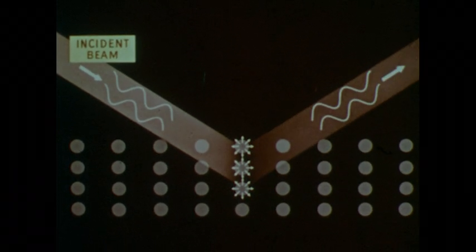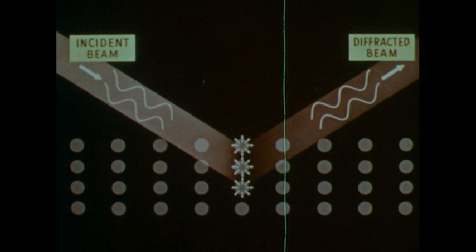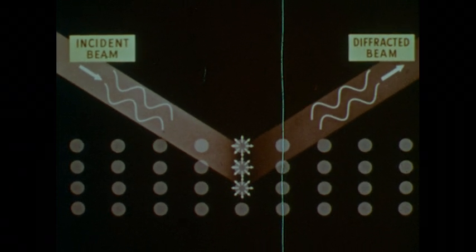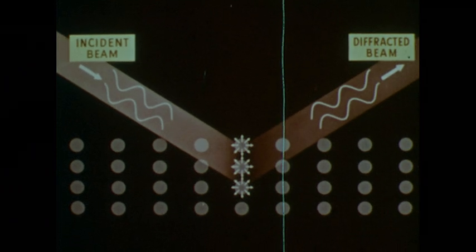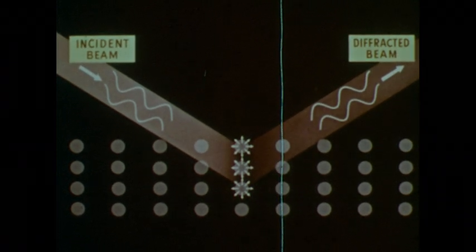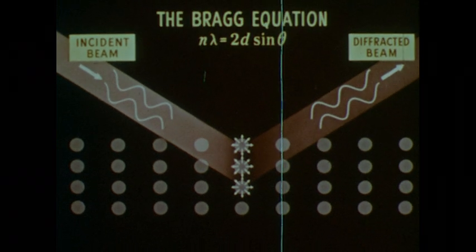As early as 1897, crystallographers suspected that this regularity resulted from a regular arrangement of atoms in the crystal. Then in 1912, this was proved through the use of X-rays, which fall on the crystal and are cooperatively scattered from the various atoms to give a diffracted beam. A diffracted beam will occur only when the Bragg equation is satisfied.